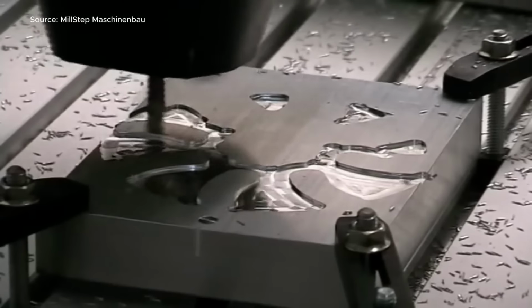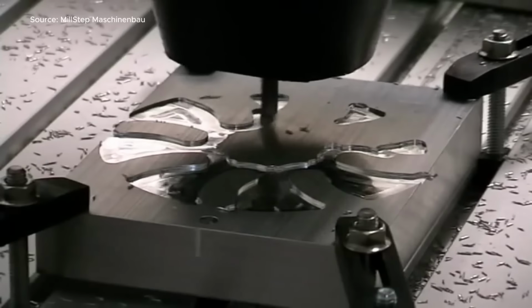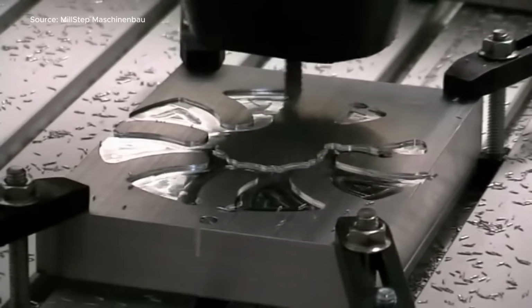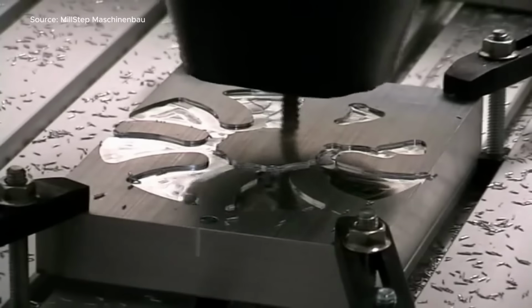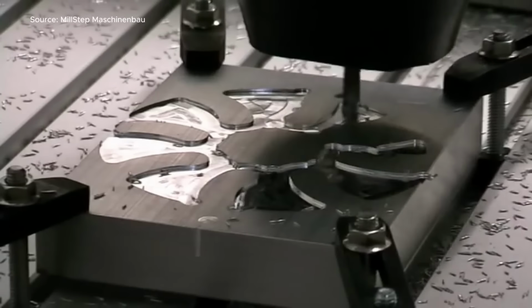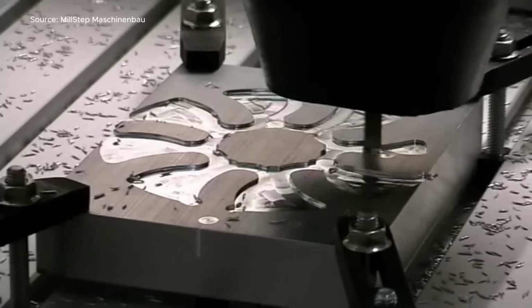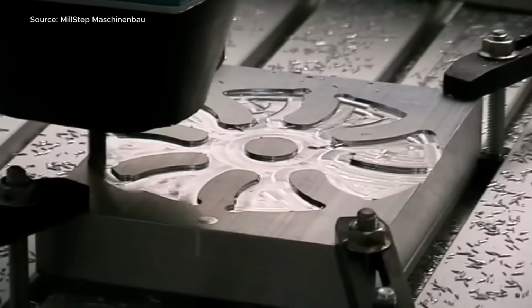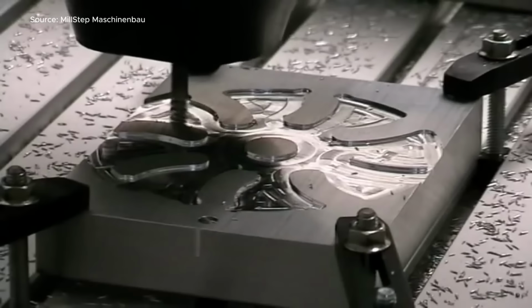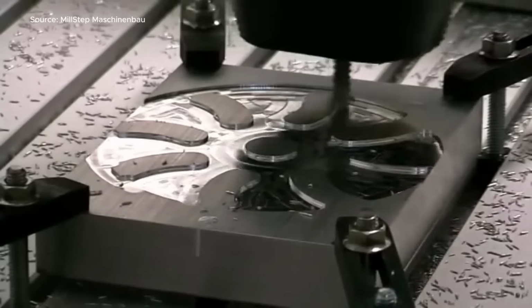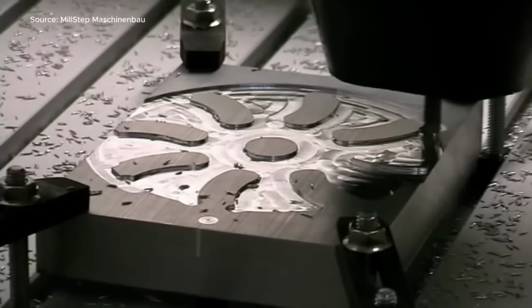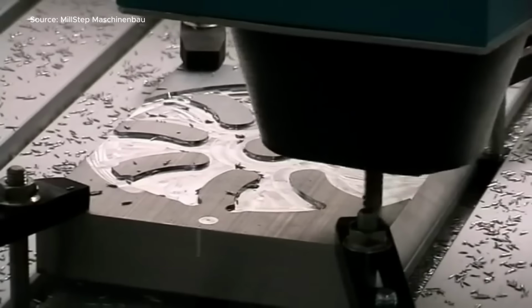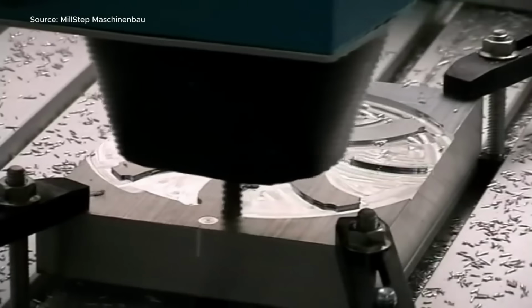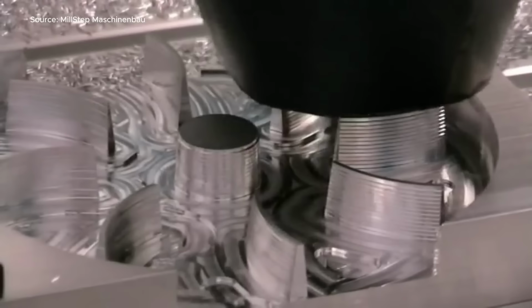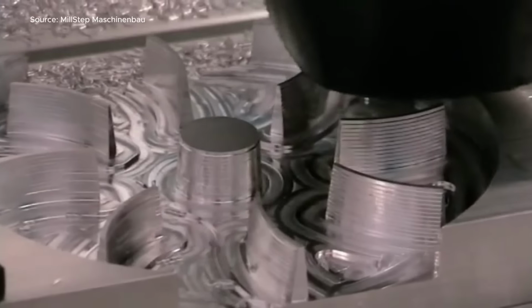Next, the machine switches to circle spiral finishing with a 6mm ball end mill. Here, the tool follows a 3-axis simultaneous tool path, moving at a tight 0.07mm step over and 35mm per second feed rate. Every detail, curves, surfaces, and pockets is refined in a series of smooth, coordinated moves. Watching the mill glide through aluminum, transforming blocky raw material into intricate aerodynamic blades, is genuinely satisfying for any manufacturing enthusiast.